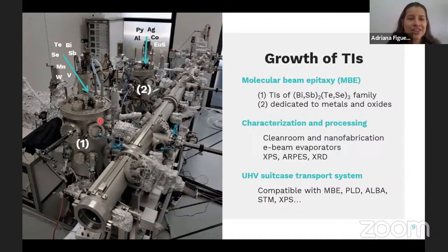So we call this a dirty chamber, sorry, because this is where we have the chalcogen atoms to grow our TIs. And we also have some transition metal atoms here that we use for doping or to make some magnetic TIs as well. And the nice thing about this chamber is that it's connected in vacuum through this vacuum tunnel to a second chamber where we can evaporate other materials. This chamber is dedicated to metals, oxides, and some insulating materials. So in this chamber, we can evaporate, for example, magnetic materials such as permalloy, cobalt, or europium sulfide.